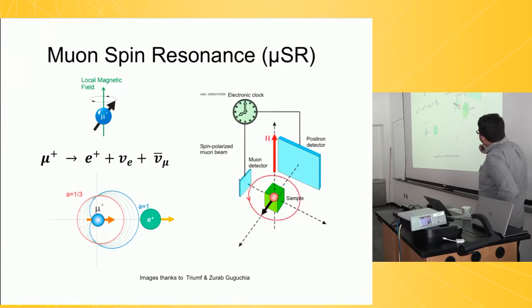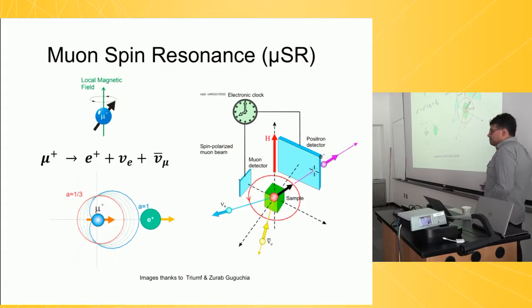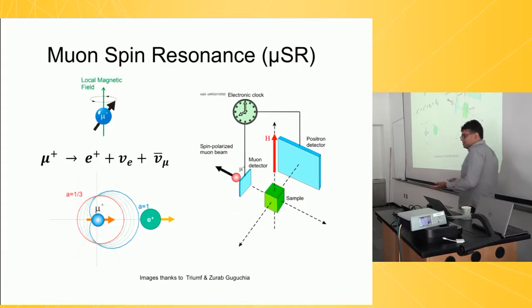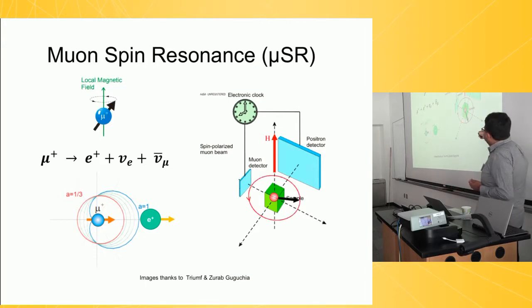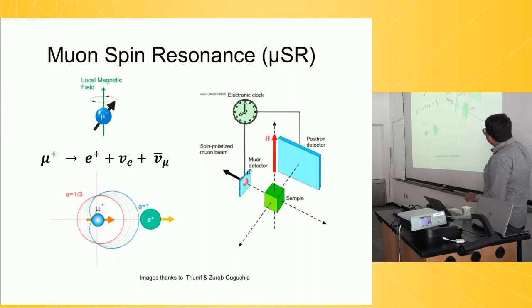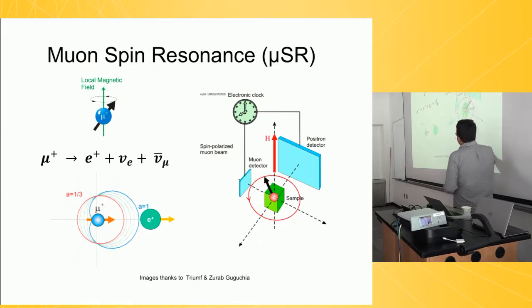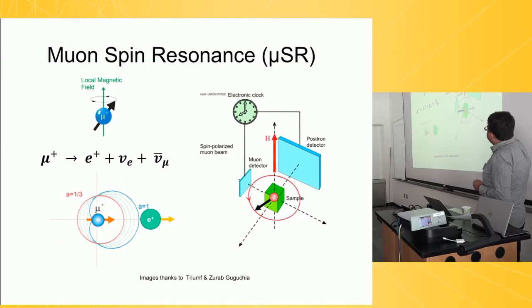So here's how the experiment works in practice. I have a muon beam which is polarized. It comes and it hits my sample. My sample could be magnetic or it could not be magnetic. If it's not magnetic, then the muon, when it comes in, is going to stick with the same spin, and when it decays, it's going to produce positrons only in this direction. On the other hand, when my sample is magnetic, then the muon is going to precess around whatever internal magnetic field exists in my sample.